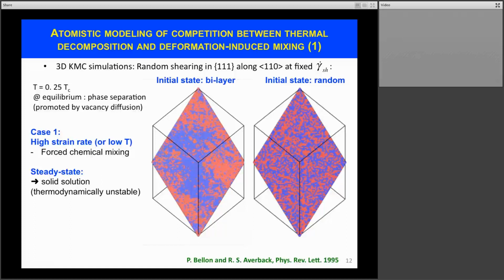but quickly the initial interface became blurred, in part by the roughening of the interface and by this forced mixing. And so now, after some time, we have reached a microstructure that is essentially random. And this is very similar to what we were looking at when we ball mill copper and silver at liquid nitrogen temperature, in the sense that in that case, thermal diffusion is very sluggish and deformation dominates the evolution of the material.